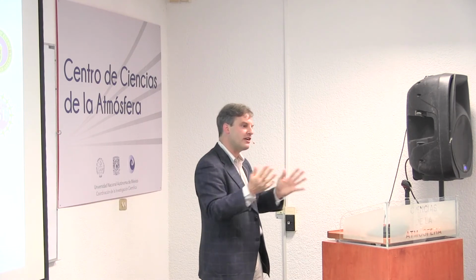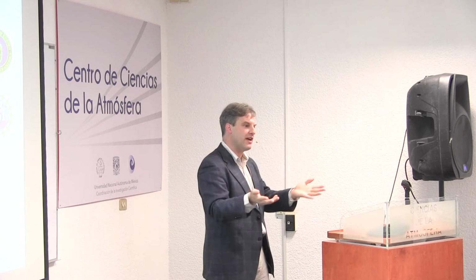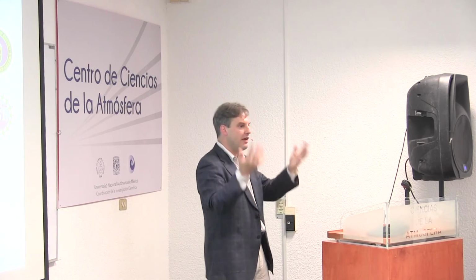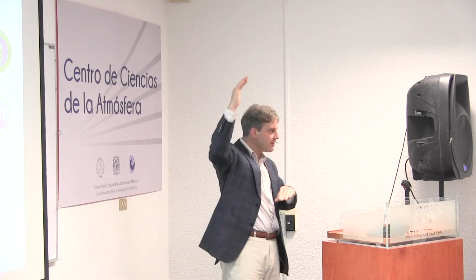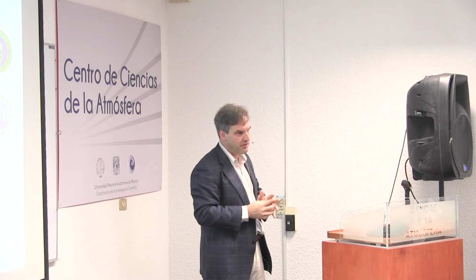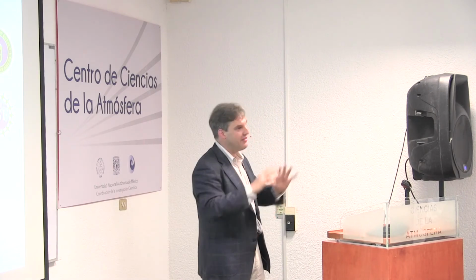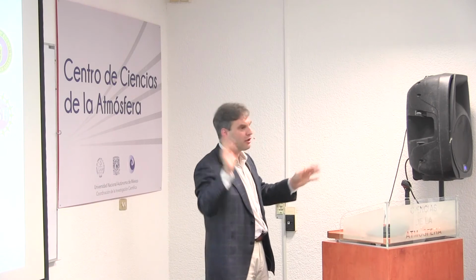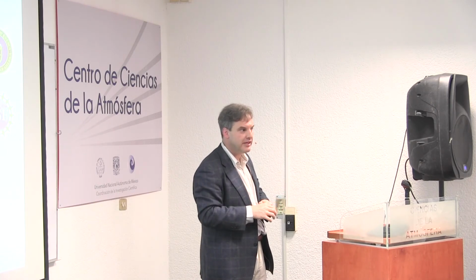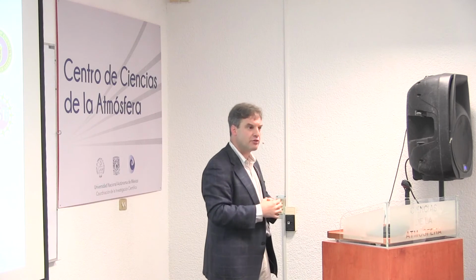They used all identified products from different SOA chamber experiments and put that in to predict the glass transition point as a function of humidity and temperature through the troposphere. There are caveats - I would not bet my life on this data, obviously - but it shows you that this is something which could be important.